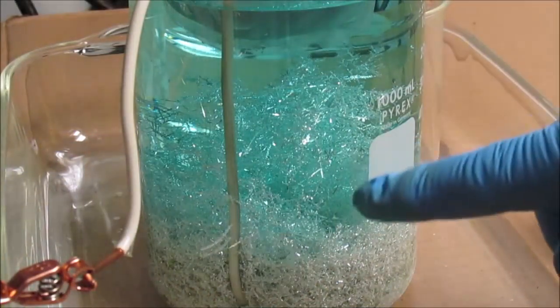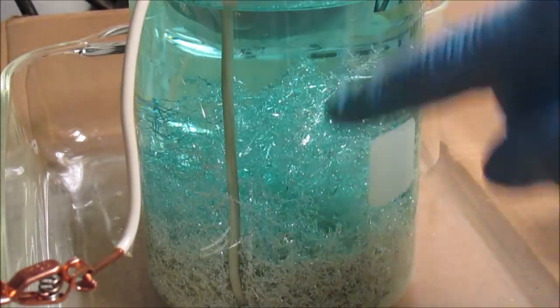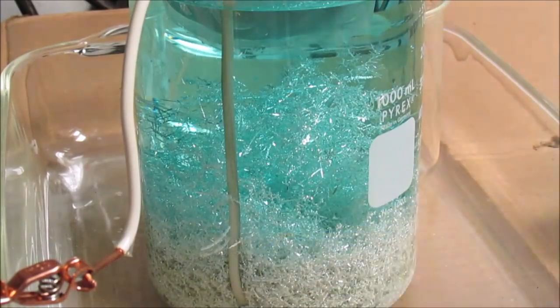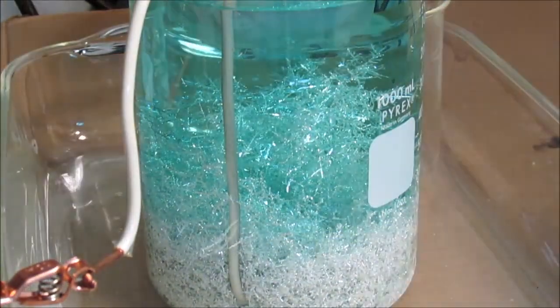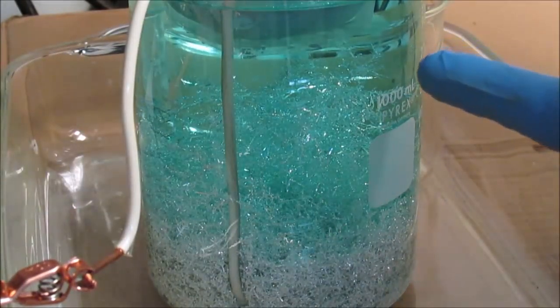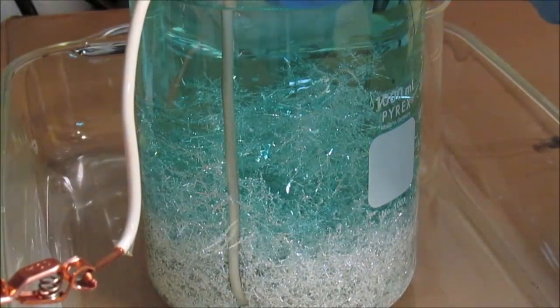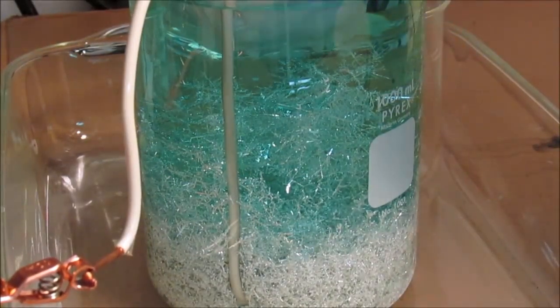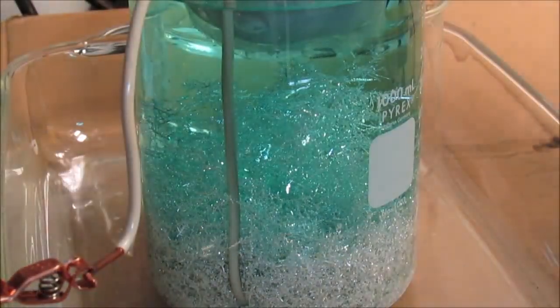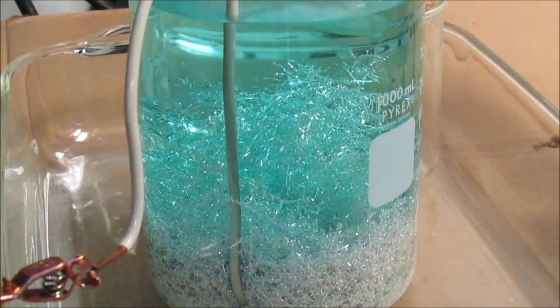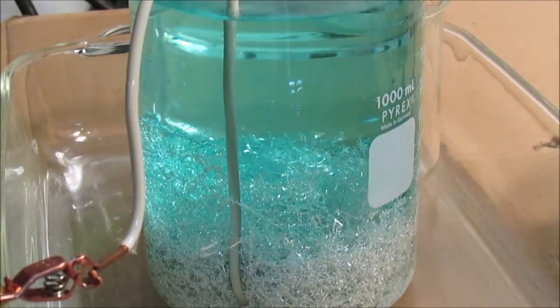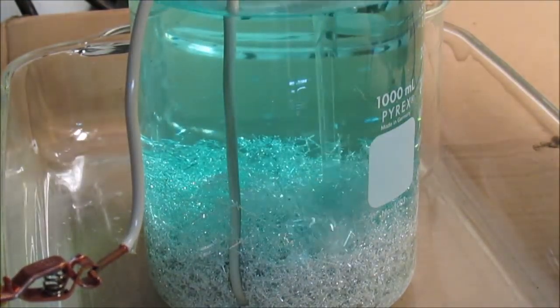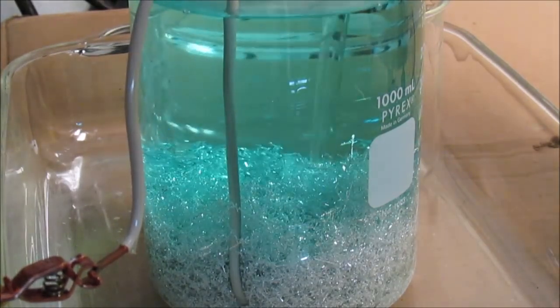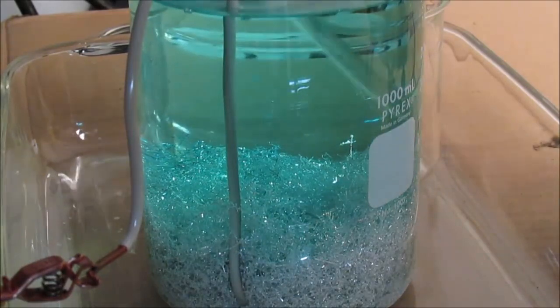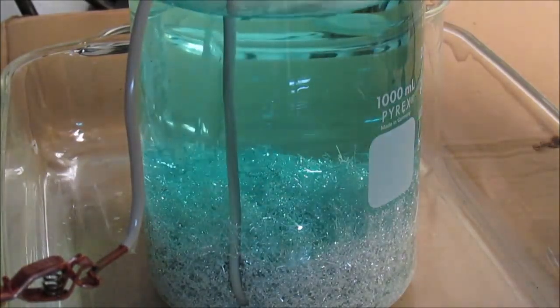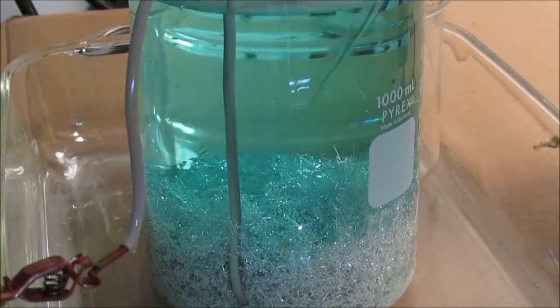This is day 4. The crystal growth is increasing. The level of silver in the cell there is starting to build up. Another 5 minutes and those crystals would begin to touch that anode bag and create a problem. So I'm going to go ahead and knock these down. Got to constantly knock these down, otherwise the crystals will contact the anode basket, burn through the anode filter, and contaminate our batch of pure silver crystal.